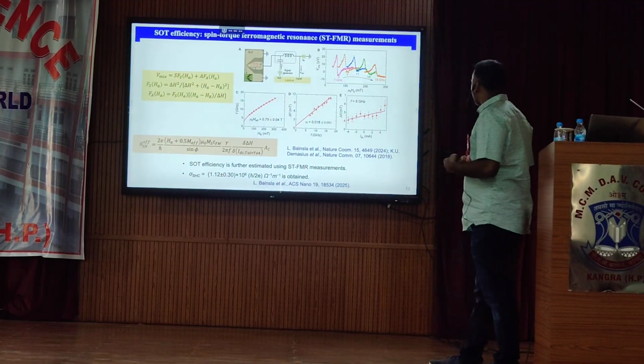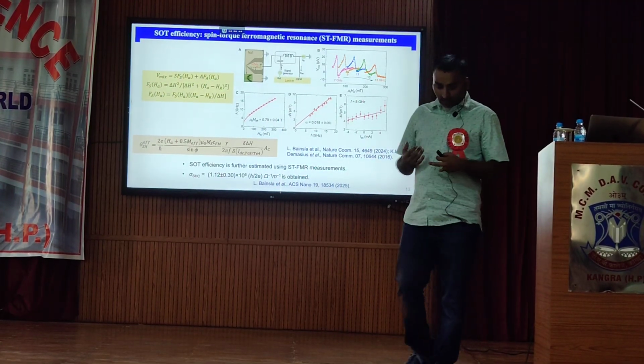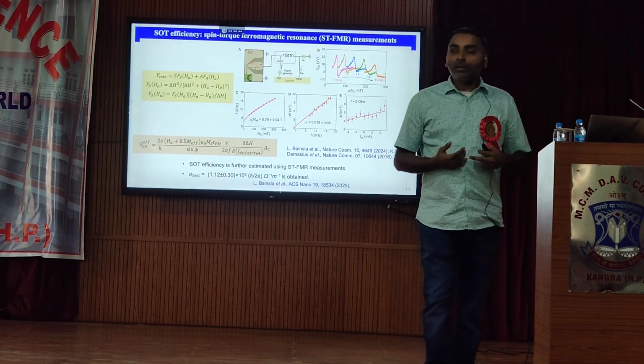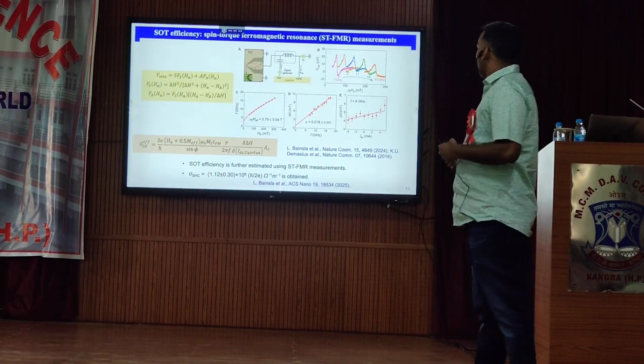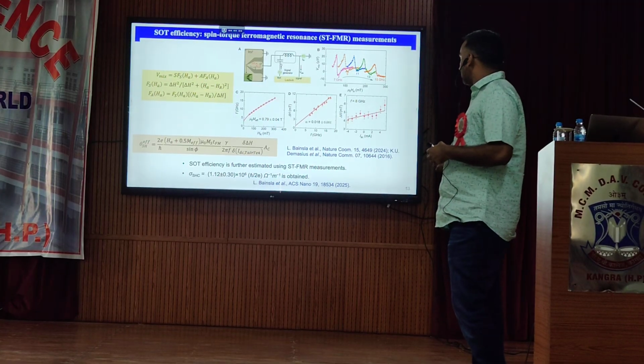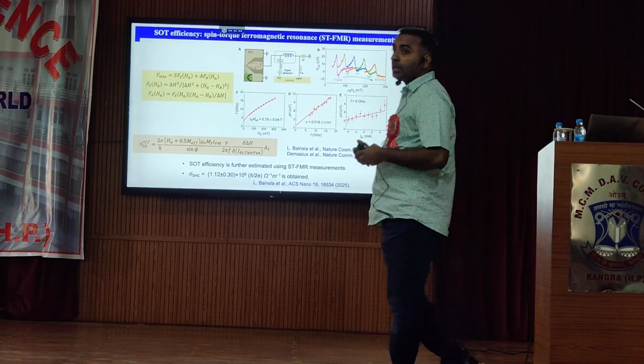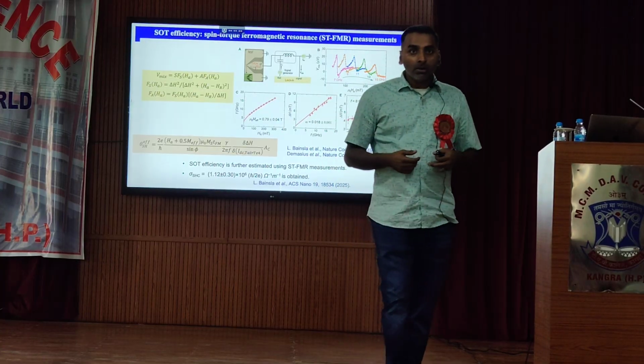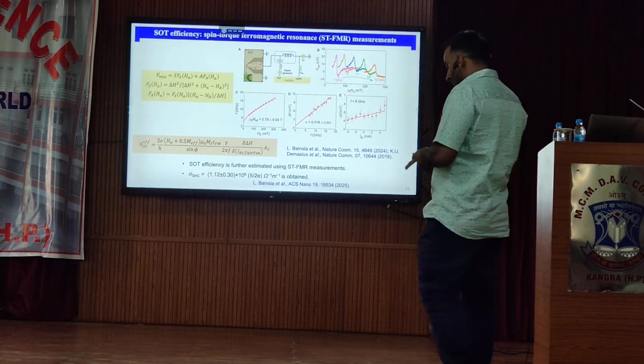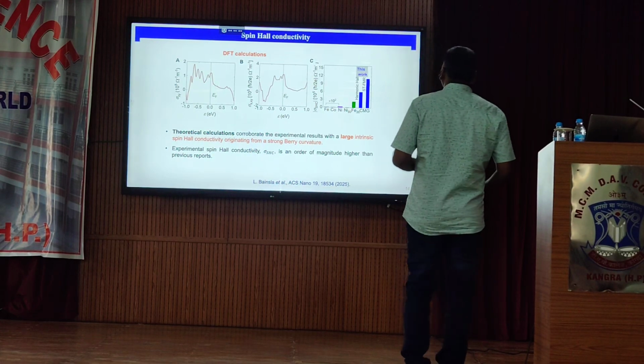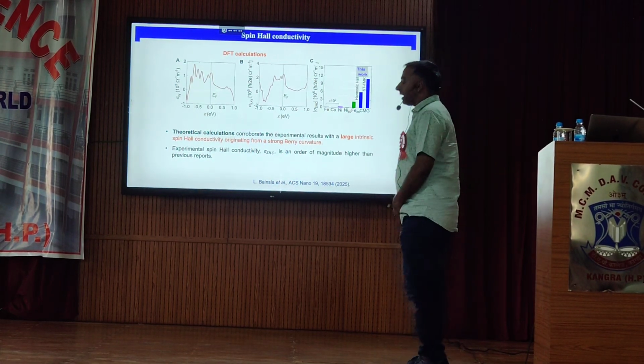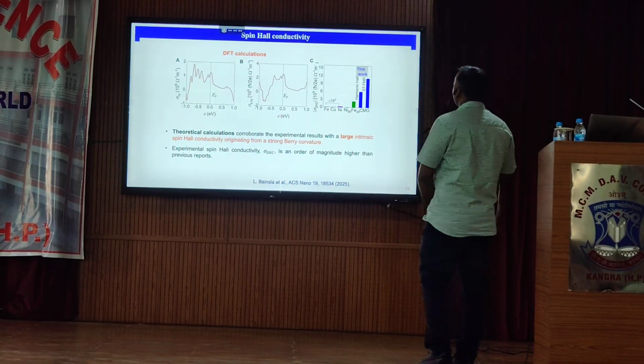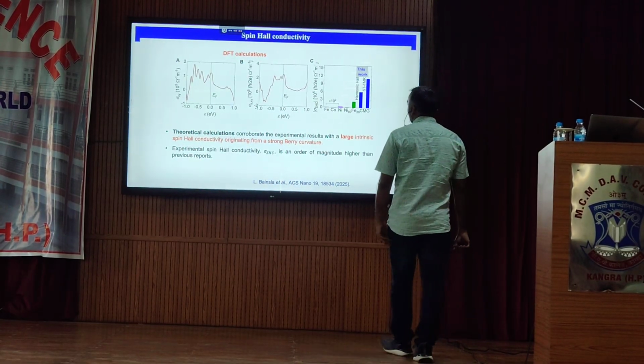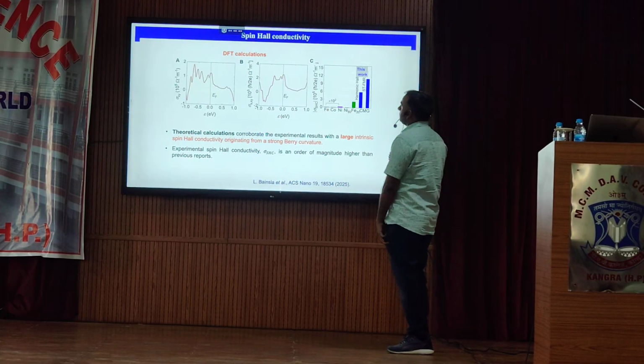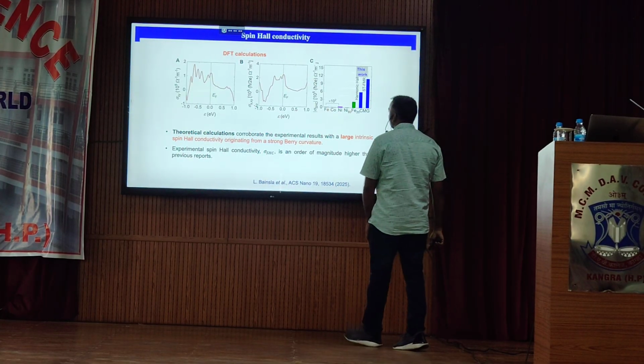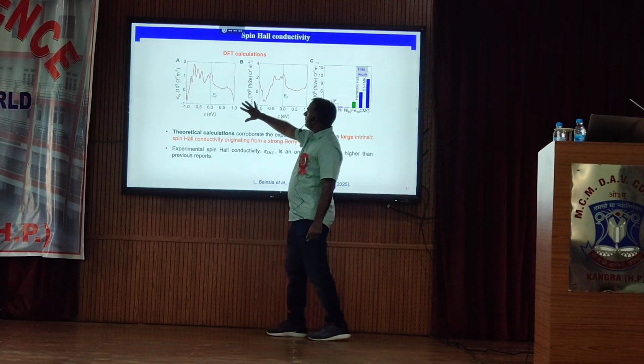So we then confirm that the spin orbit torque efficiency in this material is quite high, that we can use to get our devices like small oscillators that can operate at low temperature, and possibly using the topological materials we can also try to push the operating frequency of the oscillator. So for the spin orbit torque, since the value was very high, we wanted to confirm using theory also. Then we took help from our colleagues in Japan, National Institute for Materials Science. Then they performed calculations for the spin Hall conductivity, and the calculations are shown here.